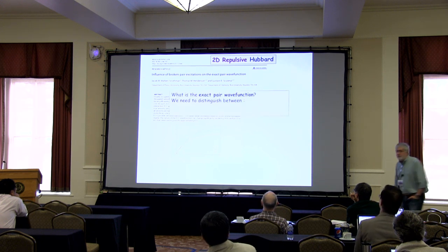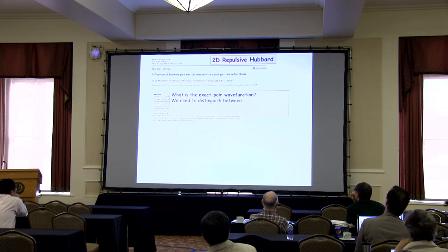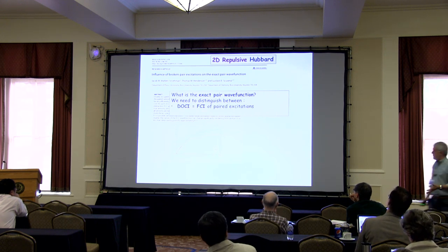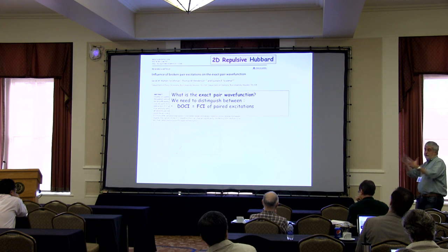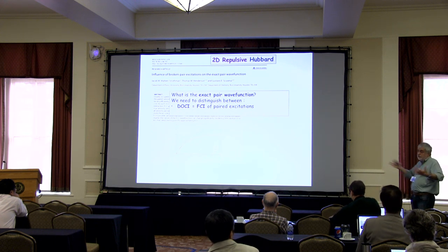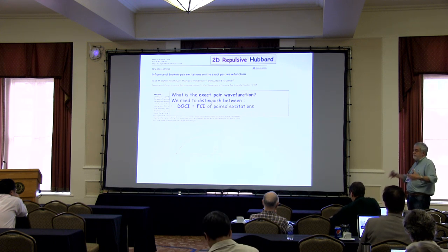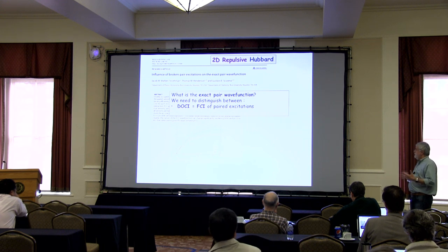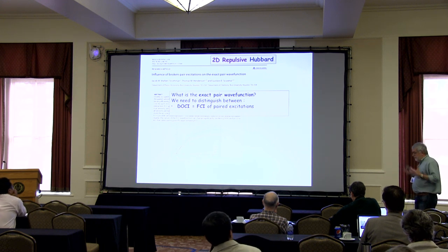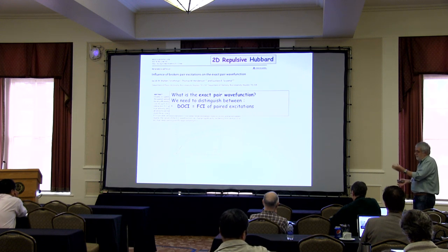We did CCSD with restricted orbitals and also CCVBSD, which is a method capable of treating some classes of strong correlation. And we found on the order of 0.15 of an electron unpaired per carbon atom, which is consistent with closed shell character. And so that's a second issue to speak to.